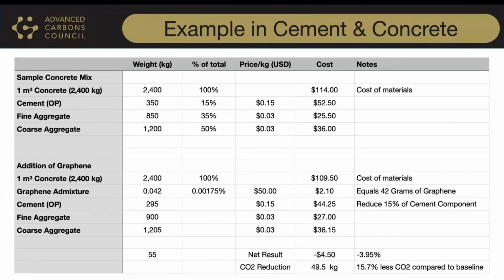In our second example, and we'll have three different price points to illustrate this, we're going to look at cement and concrete. This is a market that an awful lot of people are interested in because it's massive, and it also represents 8 to 9% of global CO2 emissions, and there's a tremendous interest to reduce that carbon footprint. So in this calculation, we've taken a cubic meter of concrete, which weighs approximately 2,400 kilograms, and then we're using ordinary Portland cement as the example. A typical formulation might be 15% of the mix is Portland cement. You can have higher or lower. This is just for illustration.